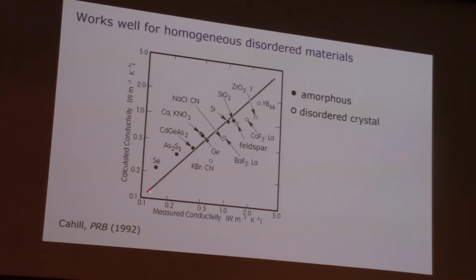So it works very well. So this is the measured thermal conductivity. This is the calculated thermal conductivity for amorphous materials and disordered crystals, what we call strongly disordered crystals, including some very important technological things like stabilized zirconia, glass. Feldspar is the major component of the Earth's crust. So this kind of physics is important in a lot of things. Solid line is perfect agreement, and you think everything kind of works out pretty well. All right, so that's where that kind of was, a long time ago.